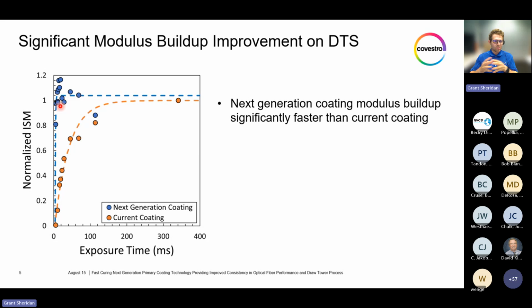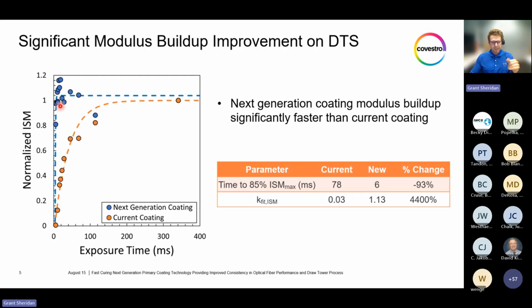Once again, we fit this to a pseudo first order kinetic equation, and we can extract a rate constant for the modulus buildup in this case. Looking at the time to achieve 85% of the maximum in situ modulus, this next generation coating decreased this time by about an order of magnitude, from 78 milliseconds down to about 5-6 milliseconds, a significant improvement. Furthermore, there's even a larger improvement in the rate constant of this modulus buildup. We see about a 2 order of magnitude increase in this rate constant, which lends to the fact that with this next generation coating, the in situ modulus more or less plateaus very quickly, after only a couple milliseconds in exposure time, leading to a more consistent in situ modulus with exposure time compared to the current technology.